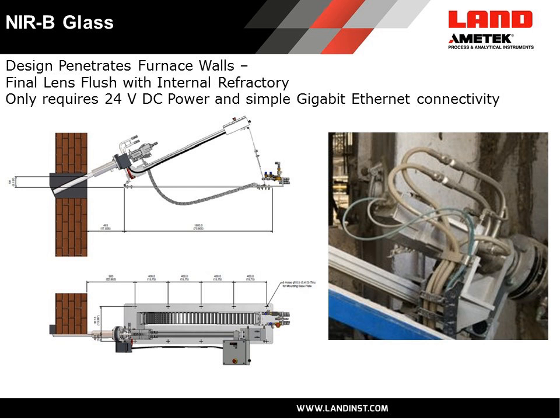So here we've got a schematic of a typical installation, and here the customer has mounted the unit high in the bridge wall, looking downwards at an angle towards the glass and towards the burner ports. And it's here at the tip of the lens tube. So our lens tube goes through a very small hole in the wall of the tank. And the tip of the lens tube is protected at this angle by having a brick cast which has a slight angle on the inside. That's just so the tip does not protrude into the gases of the furnace itself. So the tip is usually recessed around 5 millimeters into the refractory. The view from the end of this lens is a 90-degree wide view, so you see a lot of information inside of the glass tank.